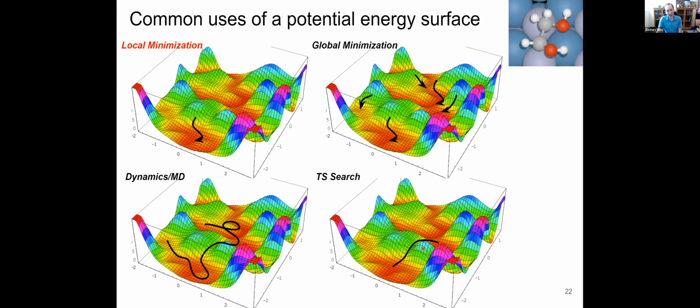But in catalysis, a lot of times it's not obvious what the individual steps are. You have simultaneous bond breaking and things moving on the surface. And so I'm not quite sure that you could do this direct prediction. What you can do is, given an initial state and a final state and a scaling relation for a type of reaction, you can often guess what the transition state energy is going to be. And there's been a lot of success in that. But I'm not 100% confident that we're going to be able to really nail down exactly what is the transition state energy without actually doing some sort of a potential energy surface.